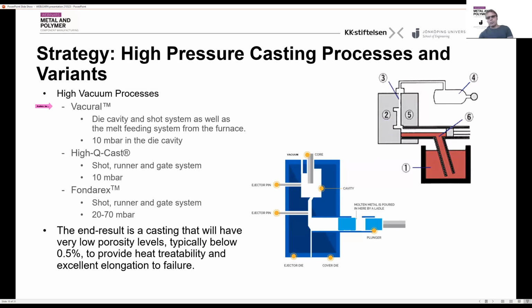And the Vacural process is actually emptying not only the die cavity, but it also empties the shot sleeve, and it's also in a way connected all the way down into the furnace compartment. And you can reach pressures as low as 10 millibars in the die cavity. And this means that if you entrain any gas inside the die cavity, it will not cause a problem. There are alternative processes like this.